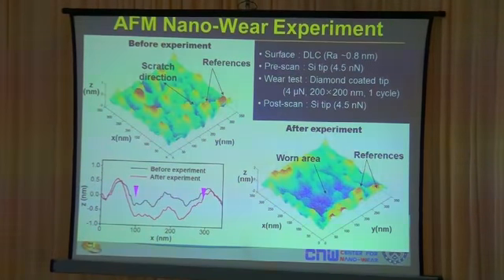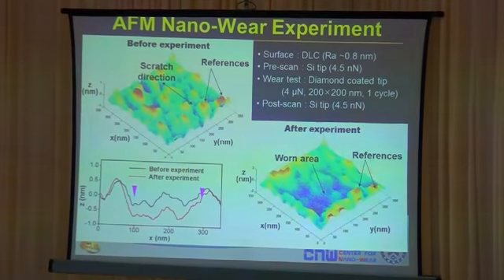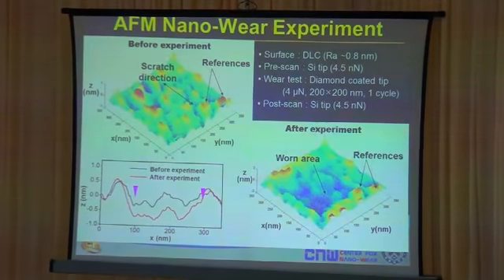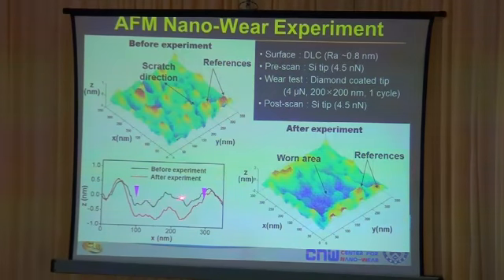You can use features on the specimen as references so that you are sure that you are in the right location, which is actually very difficult to do. If you superimpose these 2 three-dimensional images and look at it in two dimensions, you're able to see that the profile has decreased due to wear. And this is the level of accuracy at which we perform nano-wear tests. The accuracy and resolution is down to the sub-nanometer scale. Now obviously, the accuracy of this particular wear test will depend on the wear of the tip itself.